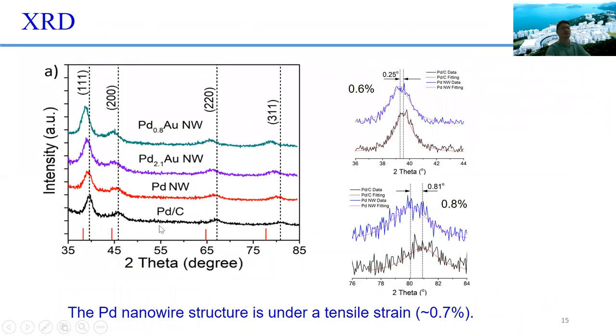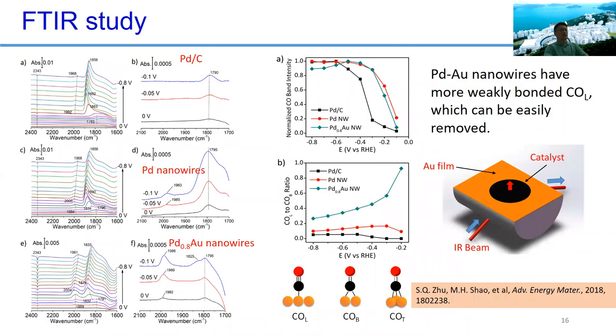So we first did the XRD diffraction pattern check. You can see that for the palladium nanowire, the peak is already slightly shifted to a lower angle. That means the palladium nanowire has a larger lattice constant than the pure palladium nanoparticle. And of course, with the gold, this peak is shifted even more. So that means there is more tensile strain in the palladium gold nanowires. We need to understand why the palladium and palladium gold nanowires had higher CO activity and selectivity.